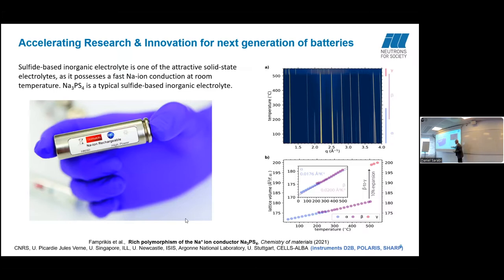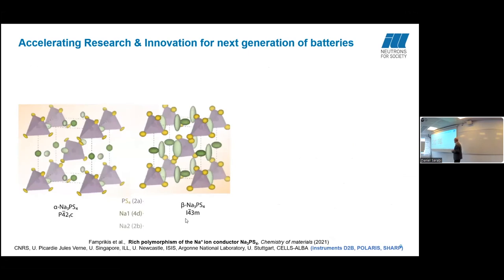This is the unit cell volume as a function of temperature, and you can see the slow second-order transition between alpha and beta, and then the very abrupt first-order transition to the gamma, that high-temperature gamma phase. And the fact that that's second-order and that's first-order has been confirmed with heat and thermal measurements. So they determined the crystal structure in the alpha and the beta phase, and what they found out was that it's tetragonal at room temperature.